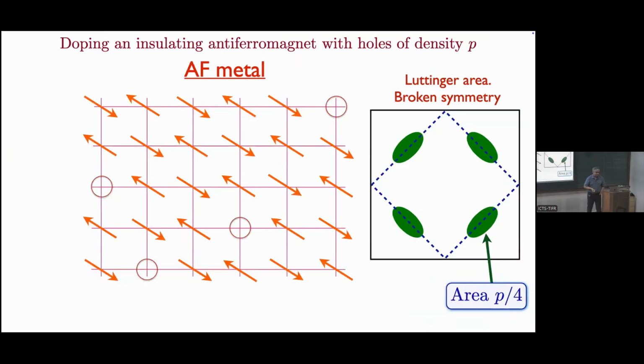Okay. Then what if you have an ordered antiferromagnet? Well, then the density modulo 2 per unit cell is just P, and so the total area enclosed by the Fermi surface should be P. On the other hand, if you do a simple calculation of free holes moving in this background, you get these 4 pockets. But really, it's not 4, it's 2, because the magnetic Brillouin zone is the dashed line, because you've broken a symmetry. So you have only 2 pockets, and a factor of 2 for spin.